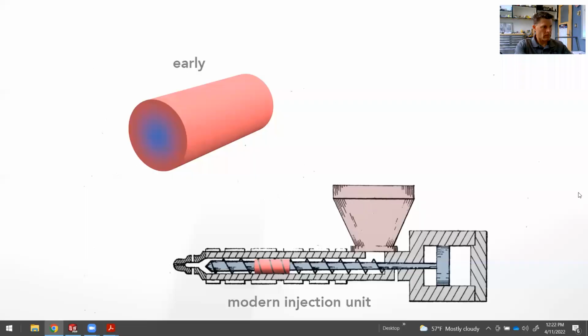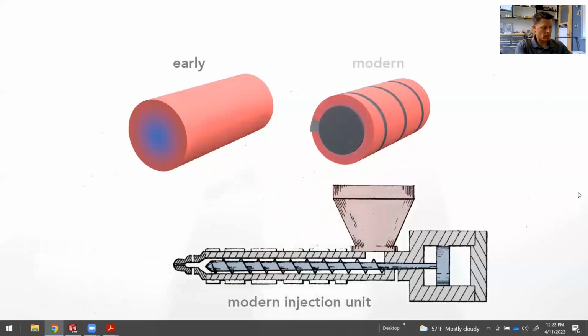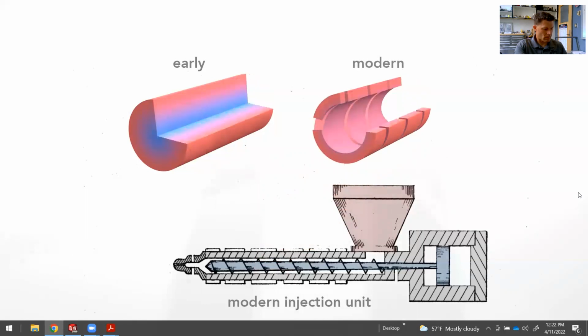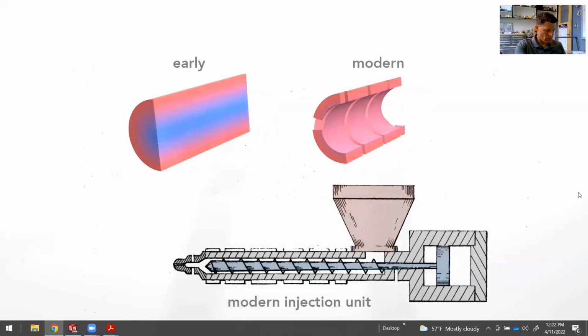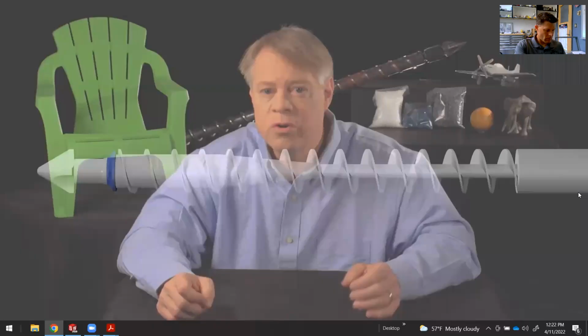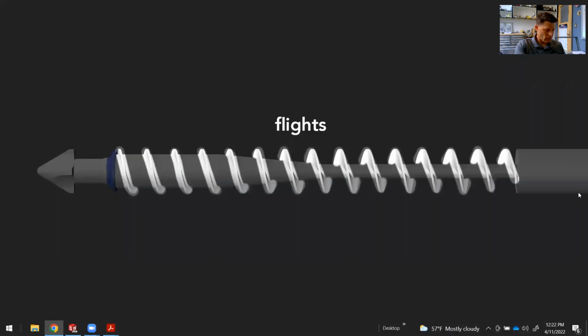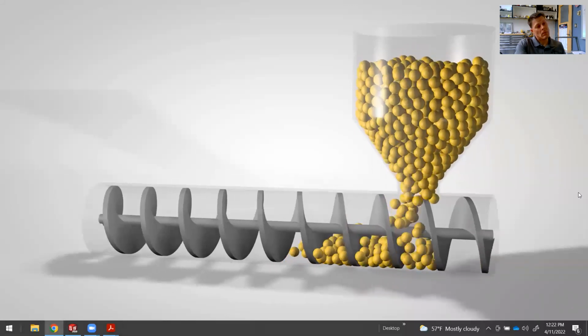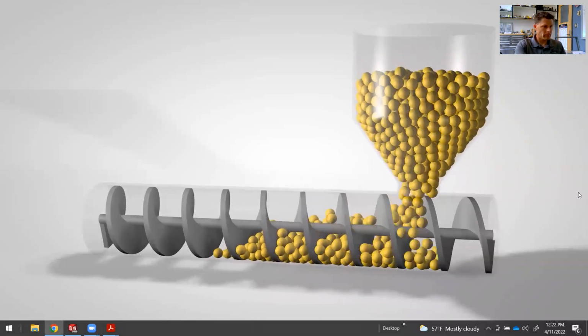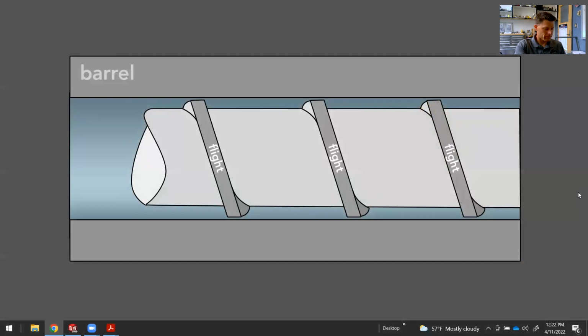The reciprocating screw overcomes this in three ways. First, in modern units, the plastic fills only the space around the shaft of the screw. This eliminates the cooler central region, leaving a thinner, evenly heated layer of plastic. Second, the screw has flights that wrap around the shaft. As the screw rotates, the flights transport the raw material forward through the barrel. The flights also serve to mix the plastic. The screw action agitates the melting pellets within the flights to create a uniform mixture. And third, the screw action itself heats the plastic throughout.